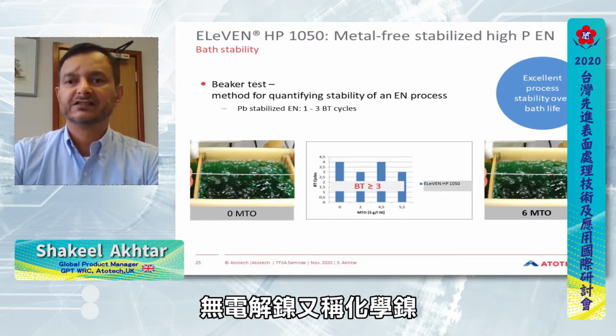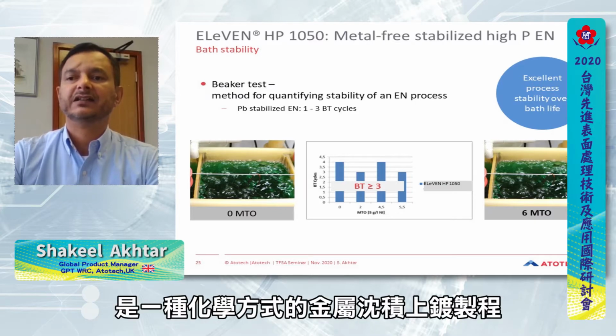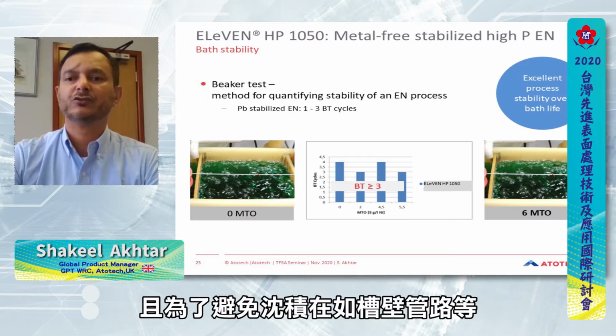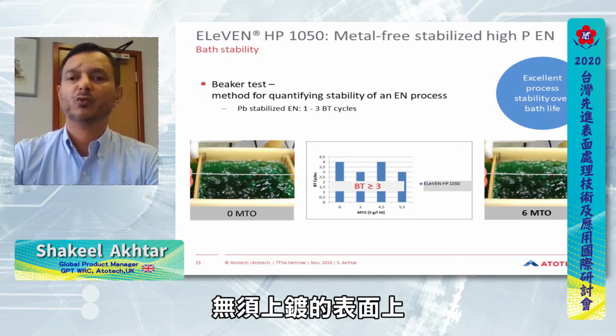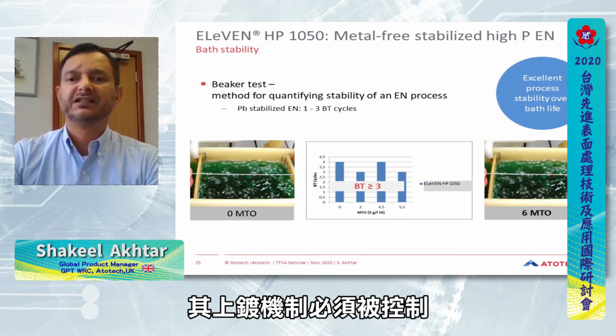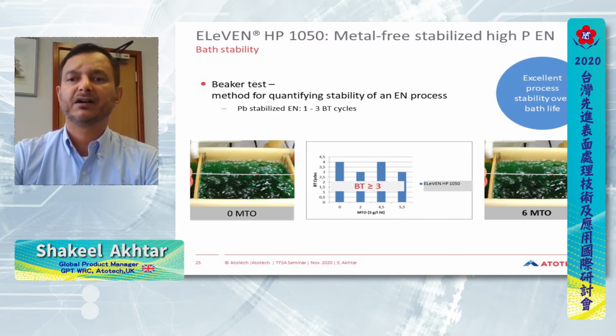The electroless nickel is a chemical process for the deposition of the metal, and the deposition mechanism has to be controlled in order to avoid plating on unwanted surfaces such as the tank walls. Thus, bath stability is an important factor to ensure a trouble-free operation. Stability in the bath is controlled by the use of stabilizers.